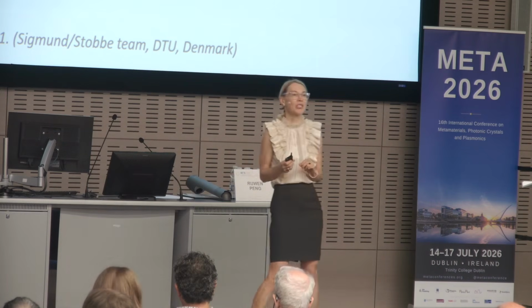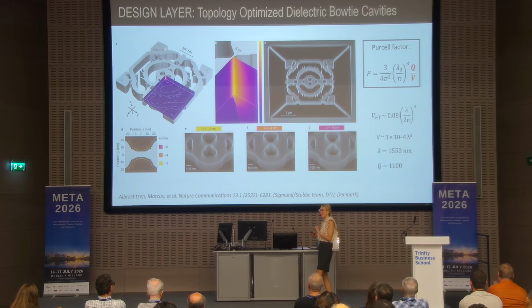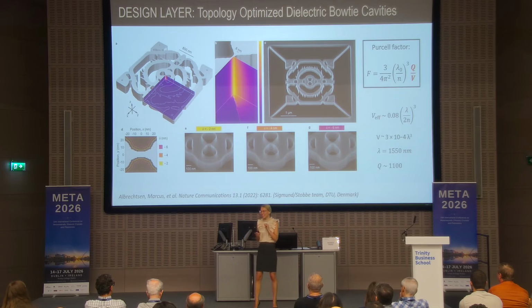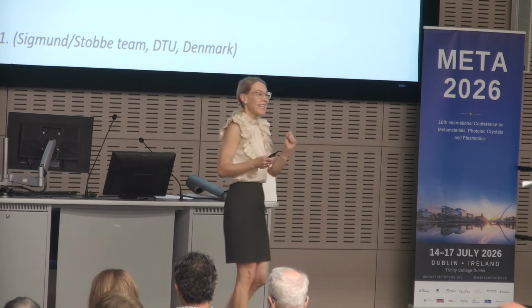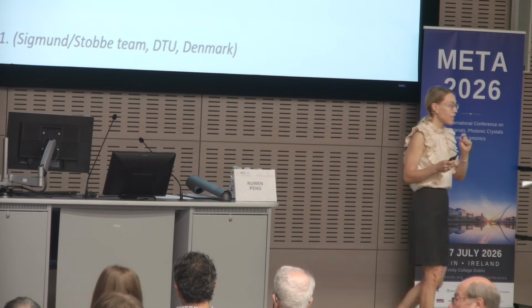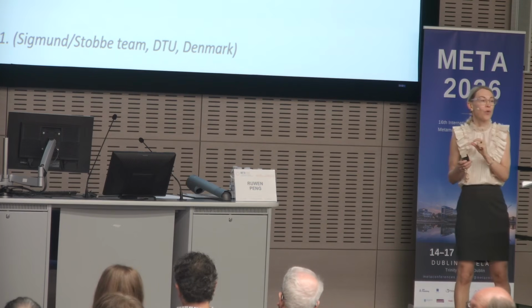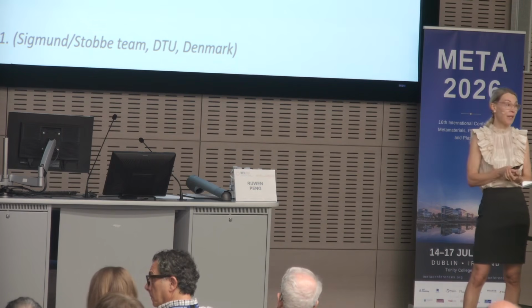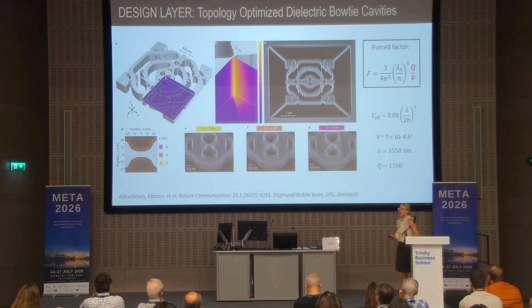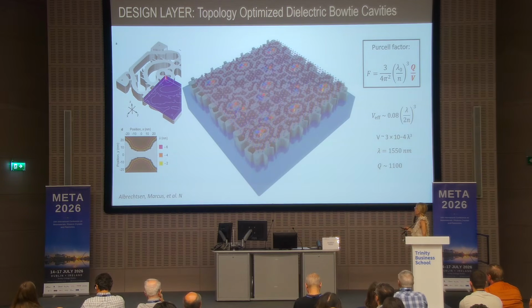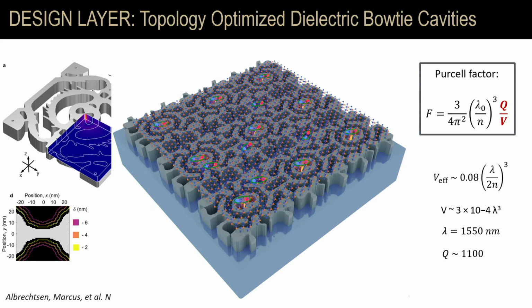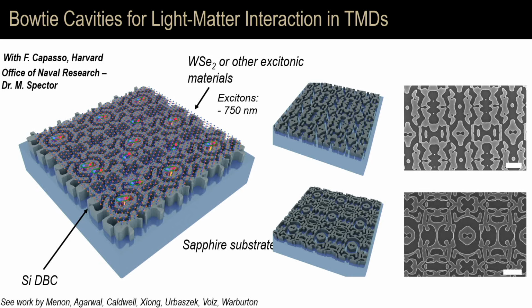Again, I don't have time to go into details, but to harness the power of topology optimization, which is also pioneered by Eli Yablonovitch largely, and others in the field, we actually can design dielectric structures that would support extremely tightly confined sub-wavelength mode volumes. And this is one of the interesting avenues for designing cavities that you can basically combine with anything. And again, in our work, what we did, we combined it with two-dimensional materials. So this is a collaboration with the Harvard team, with Federico, where we designed such a cavity, and this cavity can be combined with basically any two-dimensional materials depending on what your excitation wavelengths are.